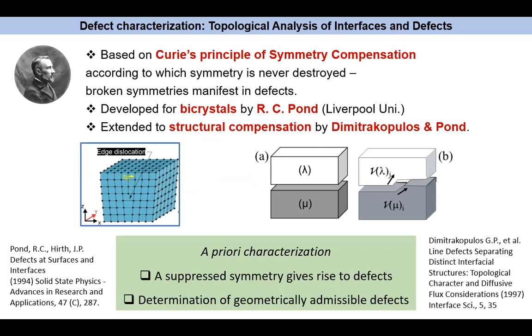Regarding topological analysis, which is primarily performed for defect characterization, this is based on Curie's principle on symmetry compensation, according to which the information that is related to the symmetry of the material is never destroyed, but in fact symmetries that appear broken manifest themselves in defects. This very important conservation of symmetry principle was later applied and developed for bicrystals by Robert Pond from Liverpool University, and then it was more generalized to more general structural compensation by myself and Pond. So this is a theory that can be employed for a priori characterization of defects.